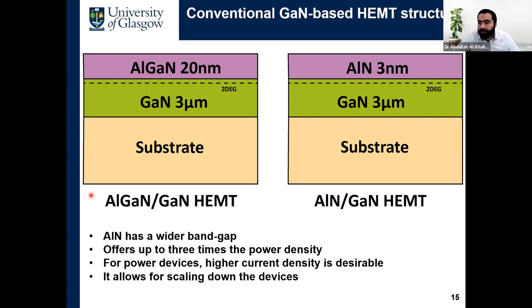Well, we do both. Ideally you want to remove the barrier. But the problem is when you remove the barrier, you kill the 2DEG. So you can aim to still etch the barrier and make side contact. But for lithography reasons, because you have an undercut in the resist, you always have a side gap between the metal and the 2DEG. Even 100 nanometer of gap will be very difficult to penetrate. So sometimes we etch halfway. So the 2DEG will be weaker, but at least you will tunnel much easier.